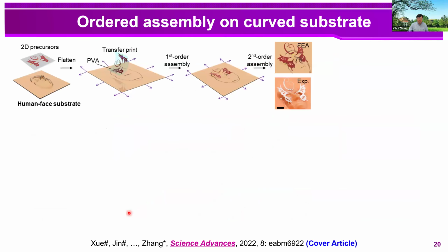So this slide shows the 2-step assembly process of the order assembly by using a human face substrate as an example. In this case, we firstly use a biaxial pre-stretch to flatten the substrate, and then apply an additional level of biaxial pre-stretch. And then we do the transfer printing. And during the release of the pre-strain, the first order assembly corresponds to the process of buckling guided assembly on a flat substrate. And the second order assembly corresponds to the pop-up of the substrate into the initial curved shape.